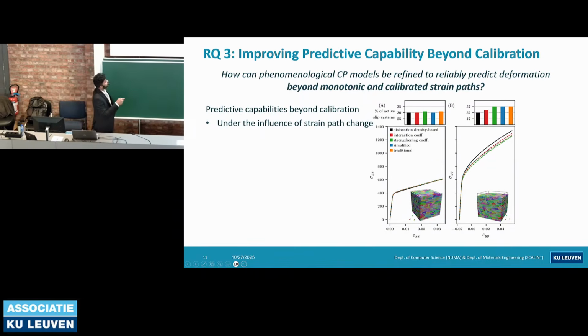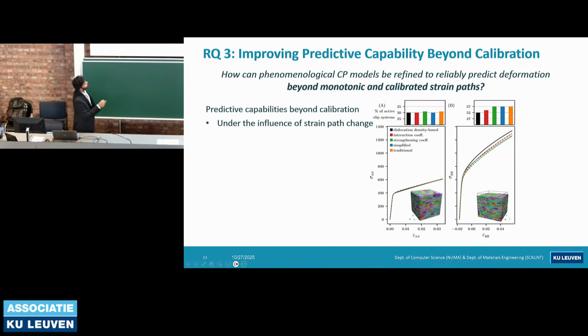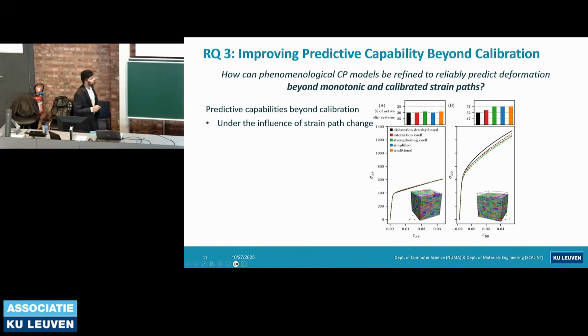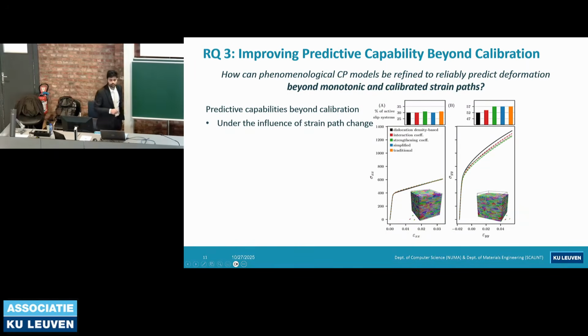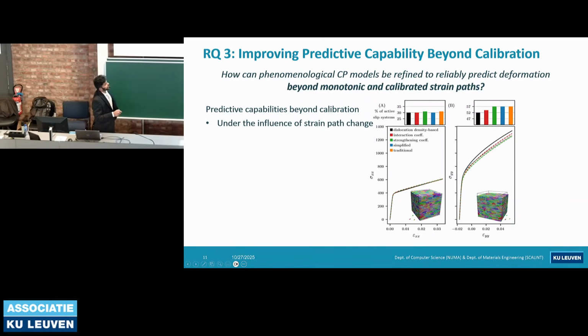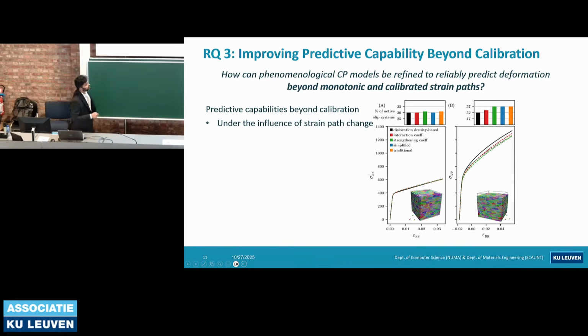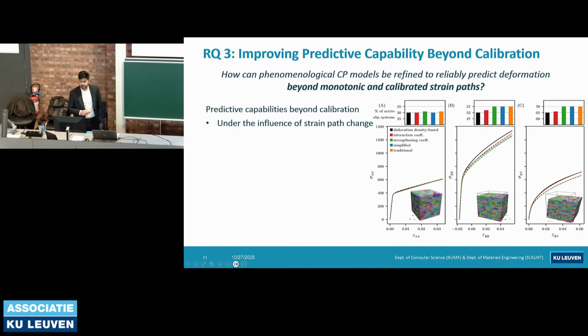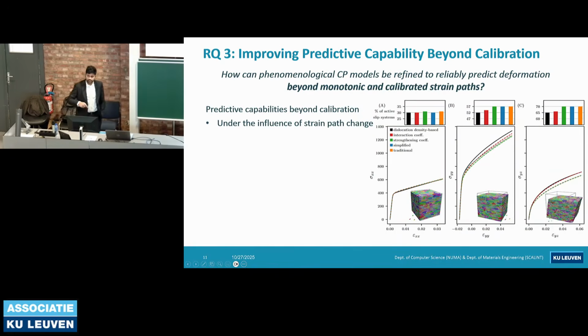Comparing, here I would like you to focus only on the black, which is the reference one, and red, the interaction coefficient parameterization, and the traditional one, which is orange. The agreement between the interaction coefficient and the reference one is closer in comparison to the traditional parameterization. Now, activating even more slip systems with the help of a shear loading cascaded on this.